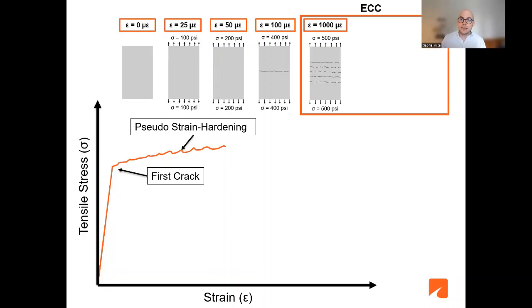And how does this mechanism occur? It occurs through this process of multiple crack formation. And this strain hardening is called pseudo-strain hardening, to be differentiated from the strain hardening observed in metals, which is based on the dislocation of atoms. This strain hardening in this cementitious system occurs because of multiple tight microcracks forming that allow this material to deform. It's important to mention that these cracks are very tight, and that's important for durability. Sometimes you can barely see these cracks with your eyes.